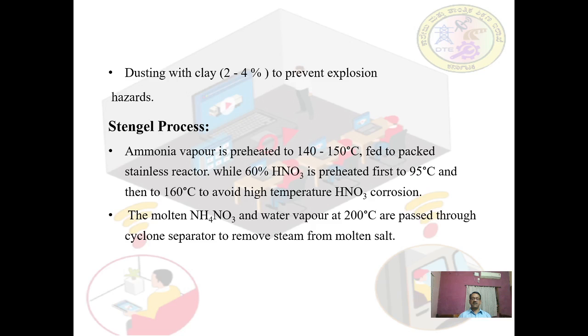Another process is the Stengel process. Here ammonia and nitric acid are reacted in vapor phase. The vapors are preheated to 140 to 150 degrees Celsius and fed to a packed bed stainless steel reactor, while 60% concentrated nitric acid is preheated to about 95 degrees Celsius and then to 160 degrees Celsius to avoid high temperature nitric acid corrosion. The molten ammonium nitrate thus formed and the water vapors at 200 degrees Celsius are passed through a cyclone separator to remove steam from the molten salt.